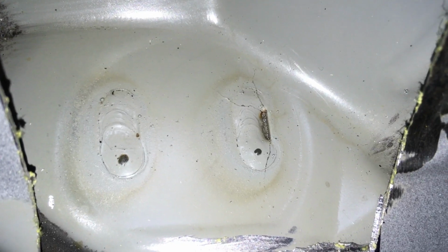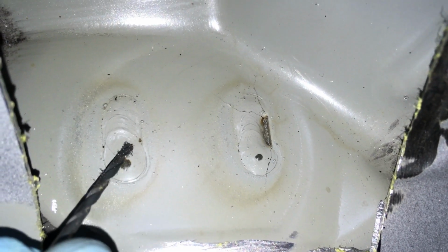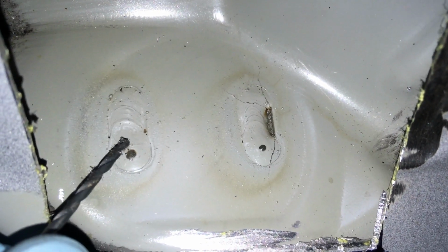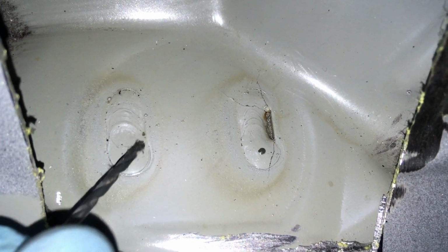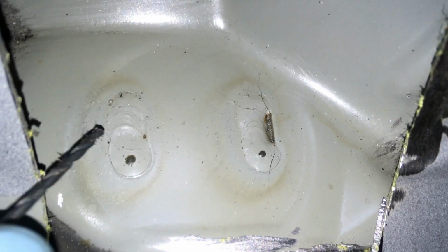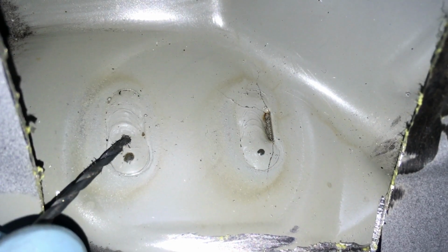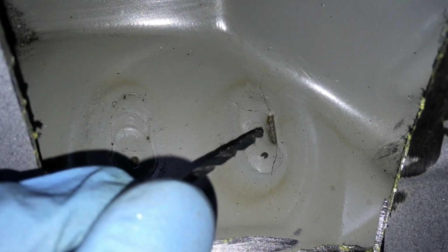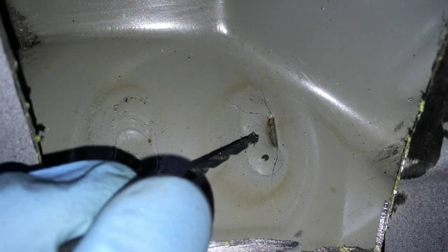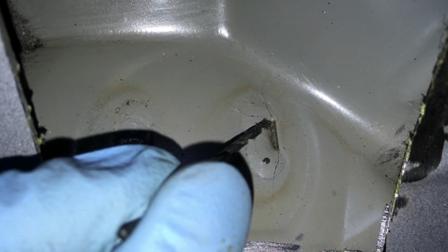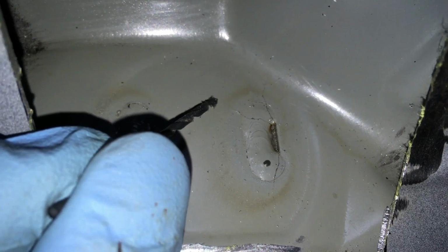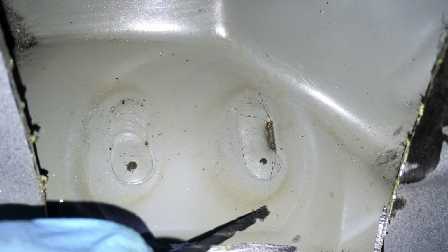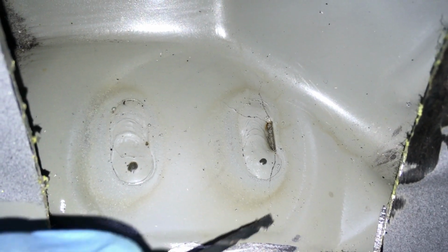Then moving on to the right hand side, these cracks are a little bit longer, tend to be on this front right side. This MIG weld is quite a good, well penetrated MIG weld. There's no gap on the side of it, nice and flat. You'll have to look very closely for cracks on that one because there's nothing obvious, but this MIG weld is quite obvious that this has got cracks. Not bad penetration, but there is a gap down the side. So we've got a crack going across the MIG weld out to about here, another crack travelling out towards the back of the car, and another crack going through the corner of the MIG weld, heading off down towards what is the front of the car down at the bottom of the screen.